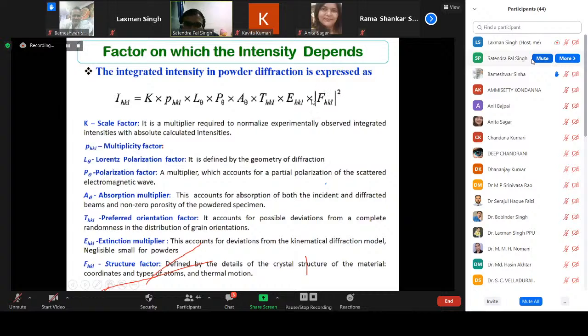So once you calculate the structure factor, we are able to determine the intensity. And we know that it depends upon the types of atoms. The heaviest atoms will deflect more X-rays compared to the lightest atoms, because X-rays are deflected by electrons. If you talk about the lightest atom like hydrogen, it is hardly deflected by X-rays, so we cannot distinguish hydrogen by using X-rays. For that case, we use neutron diffraction.